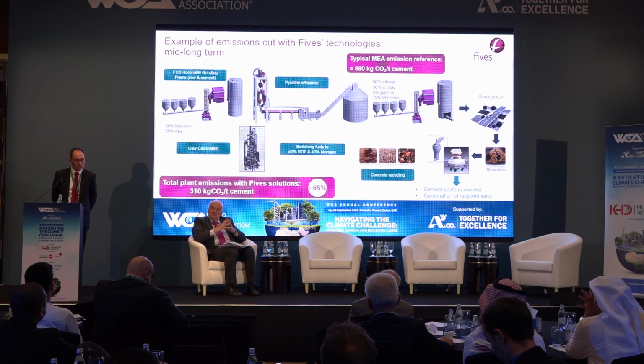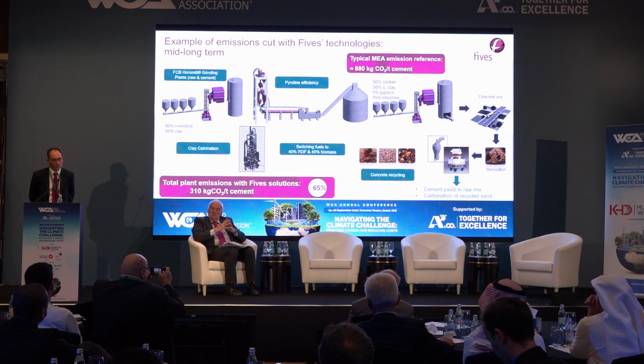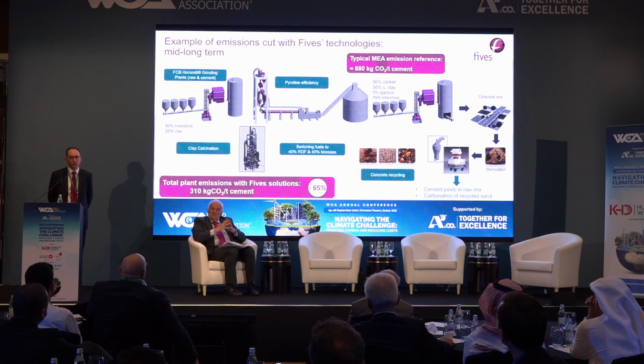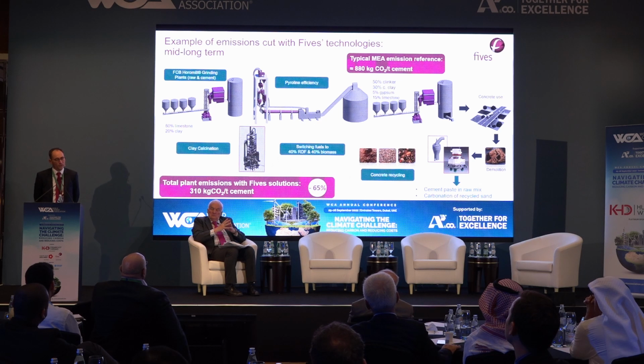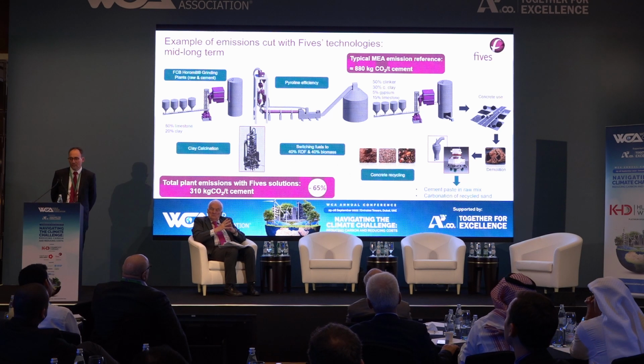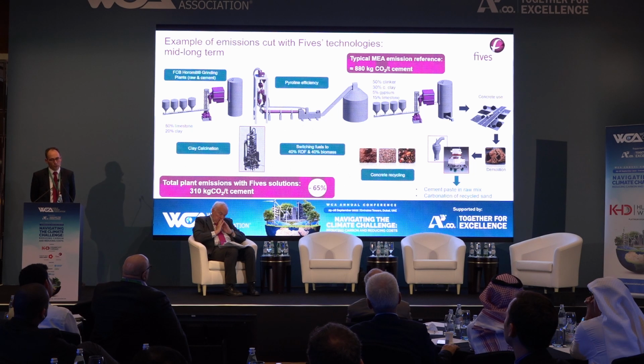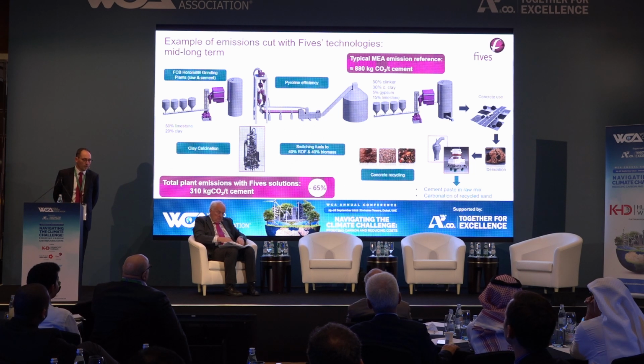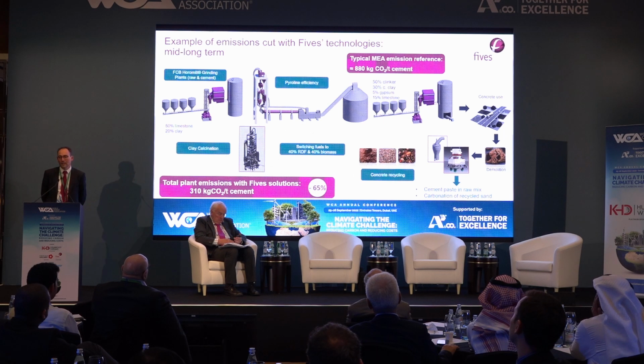But with all these technologies, at the end of the day, we offer today the possibility to reach almost 300 kilograms of CO2 emissions per ton of cement, which is quite a strong push in terms of CO2 emission reduction. We say 65%. So you have a very large panel of solutions that you can implement step by step with a different level of effect, but at the end of the day, which will allow you to reach this ambitious target and have a limited amount of CO2 to dedicate to these new technologies that are known to be costly and energy intensive.